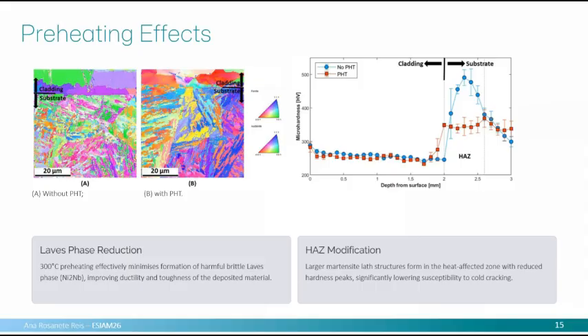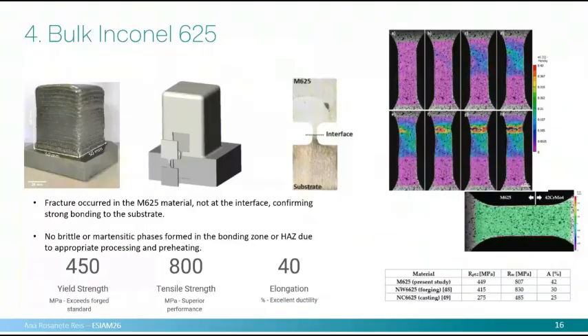So we thought about grading, because it's interesting. But before grading, we tried to do big parts in Inconel and understand a lot of things, because when you do a lot of layers, you are again imposing new thermal conditions, and we want to understand if we get good results, and also on the interface. This is also a point. So we did a lot of tests on the interface, and we got very good results. The material fails in the bulk, and we got these results for the test.